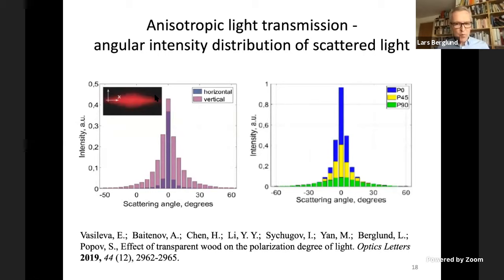The nature of light transmission in wood is actually quite interesting. It's highly anisotropic. And this is a study by Elena Vasilieva. And what she has done is that she measures the intensity distribution of scattered light. You can see here that it's anisotropic. And she measures the scattering angle distribution. And the interesting thing is that if you provide polarized light, you completely change the intensity distribution of your transmitted light.